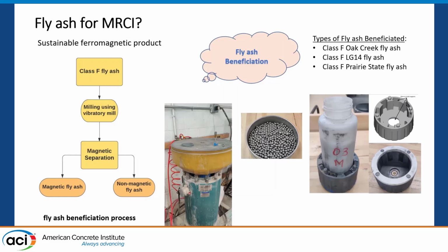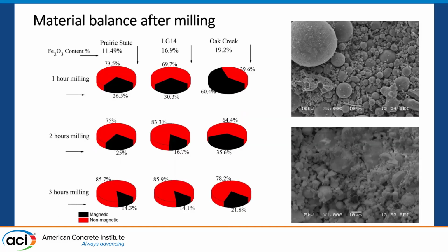Okay, so now the question was about how to make it cheaper and where we get these wonderful magnetic particles. Well, fly ash is a perfect source for us. We see less and less fly ash available for our projects. There is still fly ash deposited, and this is the setup we had for beneficiation of fly ash. Basically the idea is, can we extract magnetic fly ash from already relatively rich types of fly ash? We had a few products ranging from 11% to almost 19% iron oxide, and those were perfect candidates to study.